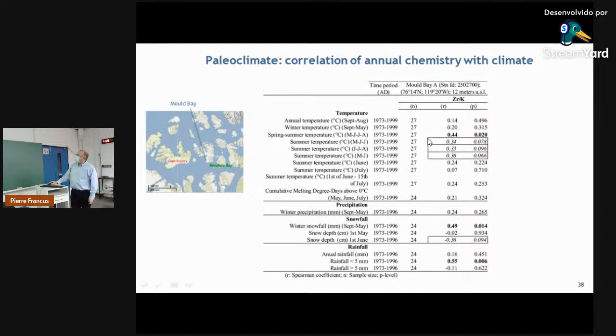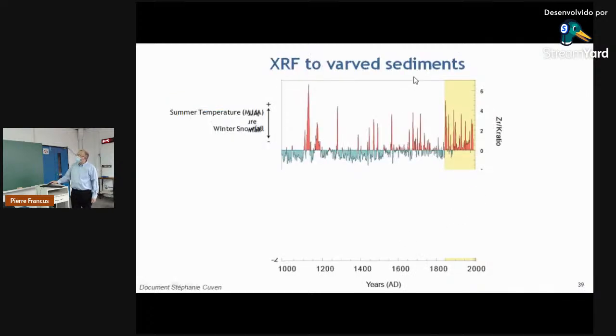And so here, the strongest correlation is with the temperature for May, June, July, August. And then we also have a good correlation with the amount of snowfall during the previous winter. So we can then plot our zirconium to potassium ratio on a calendar scale. So here we have 1,000 years. And you can see really that in the last 150 years, we have an increase in summer temperature and also an increase in winter snow. And you can see here, basically, it was colder. That's probably what we call the Little Ice Age. But around these years, and this is quite common in the Arctic, you have warmer years.